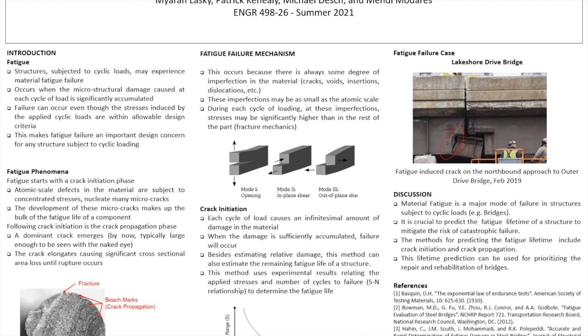The fatigue failure mechanism occurs due to some degree of imperfections, such as voids, cracks, inclusions, and dislocations. During cyclic loading, stress at imperfections is significantly higher than in the rest of the part. Shown in the diagram in the middle are 3 common modes of fatigue failure: opening, in-plane shear, and out-of-plane shear. The highest stress concentrations occur at the tips of the cracks in each case. This mechanism is why fatigue failure can occur at loads within allowable design criteria.